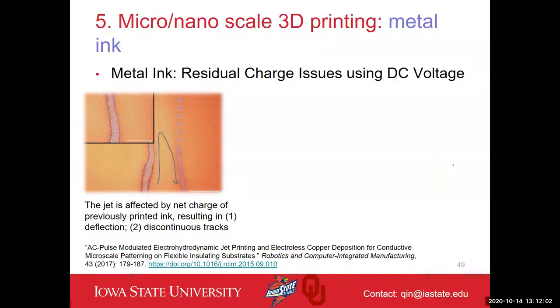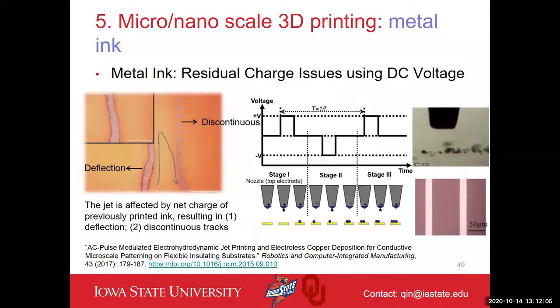the future printing quality. So in my group, we use pulsed AC voltage so that we can specifically control the droplet generation. We generate a positively charged droplet first, and then generate a negative charge to charge the particle, and the two will neutralize each other. So that's how we can achieve good printing on any substrate that we want. So this idea has been successfully implemented for device fabrication.